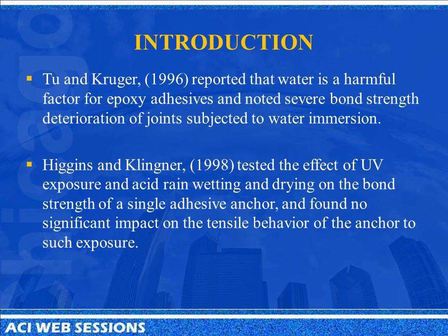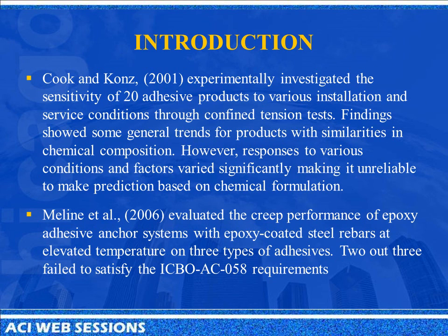I'm just going to do a little bit of literature review regarding the subject. Tu and Kruger in 1996 reported that water is a harmful factor for epoxy adhesives and noticed severe bond strength deterioration of joints subjected to water. Also, Higgins and Klingner in 1998 tested the effect of UV exposure and acid rain wetting and drying on the bond strength. No significant impact on the tensile behavior of the anchor was noticed. Cook and Konz in 2001 experimentally investigated 20 different types of adhesives under different service and installation conditions. Although they found some general trends for products with similarities in their chemical formulation, within those chemical groupings some variation did occur, which makes it unreliable to make any predictions based on chemical formulation.